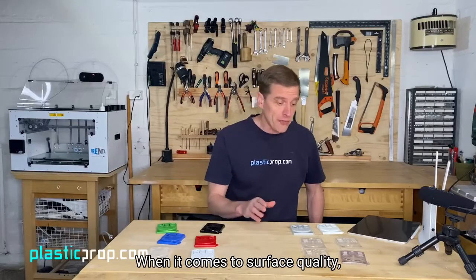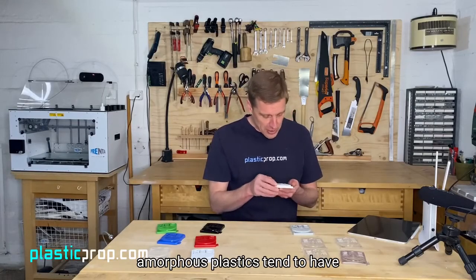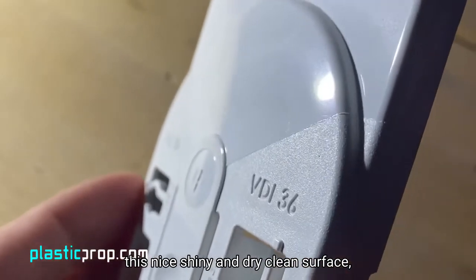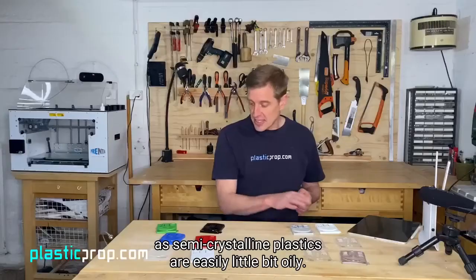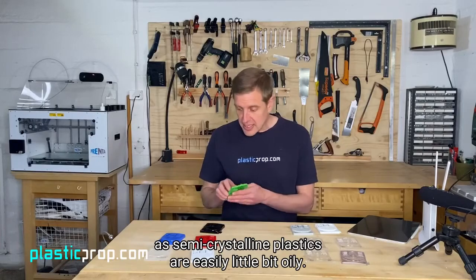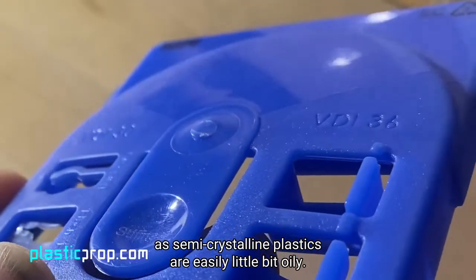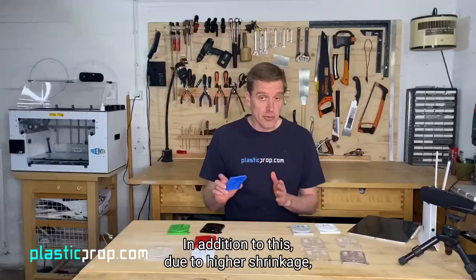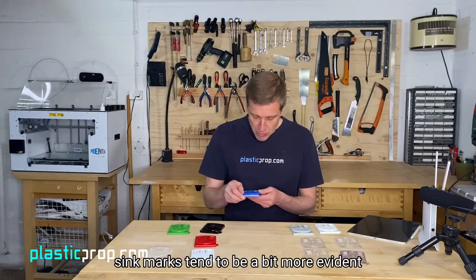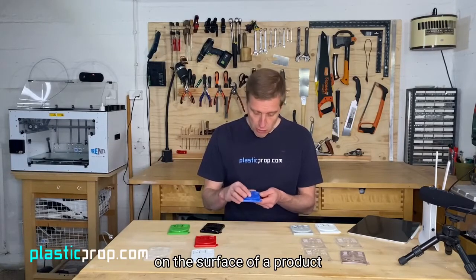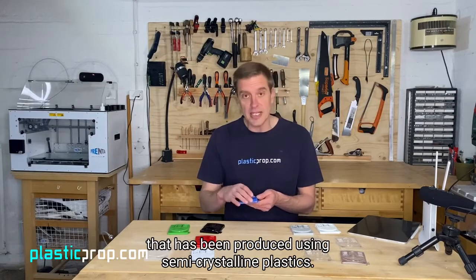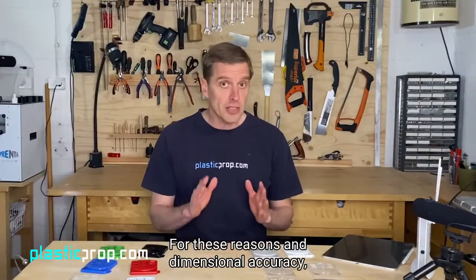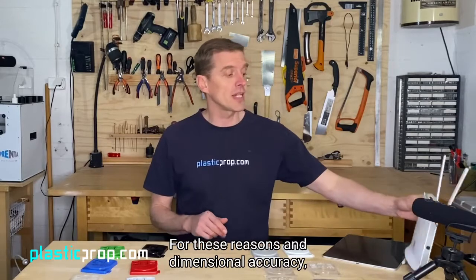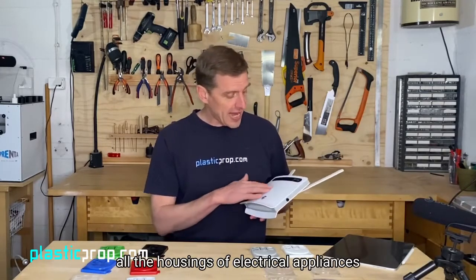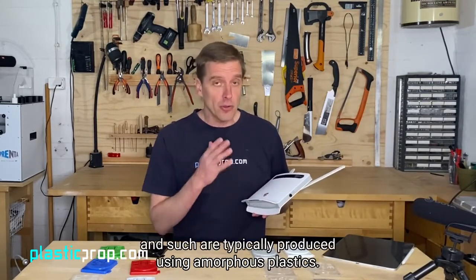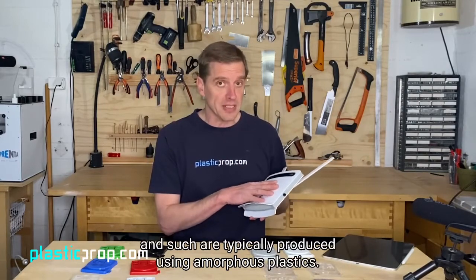When it comes to surface quality, amorphous plastics tend to have this nice, shiny and dry, clean surface, while semi-crystalline plastics are easily a little bit oily. In addition to this, due to higher shrinkage, sink marks tend to be a bit more evident on the surface of a product that has been produced using semi-crystalline plastics. For these reasons and dimensional accuracy, all the housings of electrical appliances and such are typically produced using amorphous plastics.